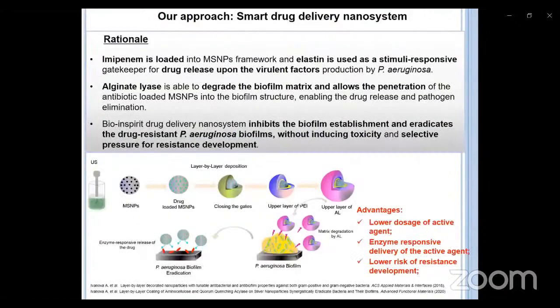So herein we have developed smart drug delivery nanosystems. Imipenem is loaded into mesoporous silica nanoparticles frameworks, and elastin is used as a stimuli responsive gatekeeper upon the elastase production by Pseudomonas aeruginosa. Alginate lyase breaks down the biofilm matrix and allows the nanoparticles penetration into the biofilm structures, enabling the drug release and eliminate the pathogen.